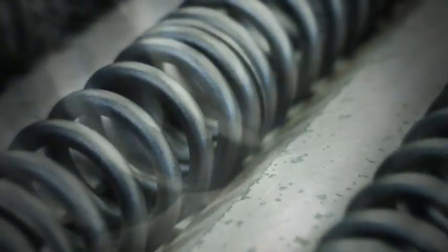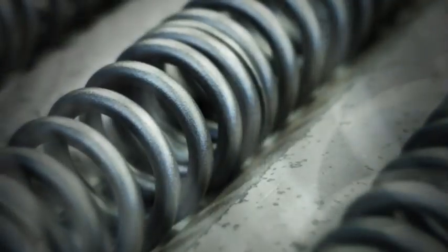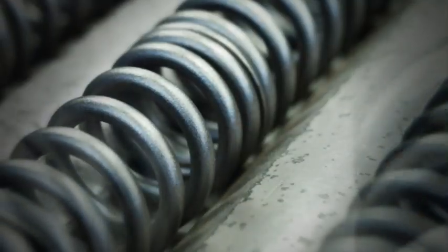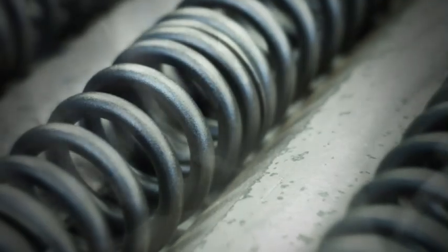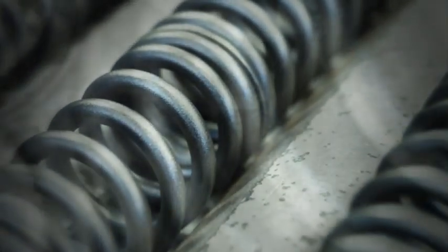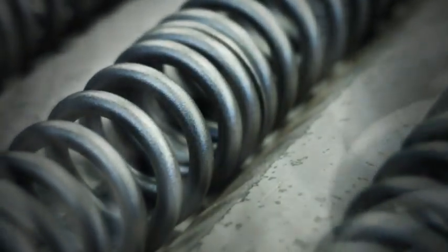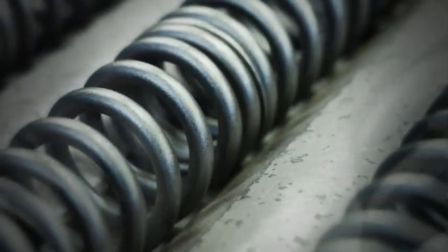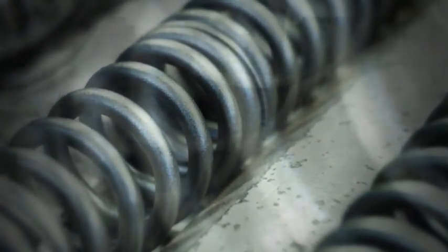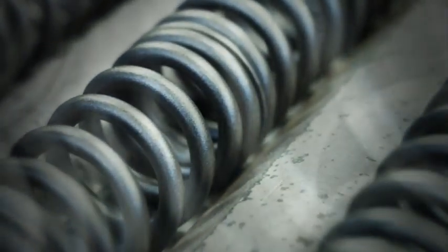A sample may run for millions of cycles. Failures are recorded by location and life. The test can compare material, peening, heat treatment, or geometry. No laboratory test reproduces every field condition. Road salt, grit, misalignment, random shock, and temperature variation may create combinations difficult to accelerate faithfully. Testing still reveals process drift and provides a rational basis for design.